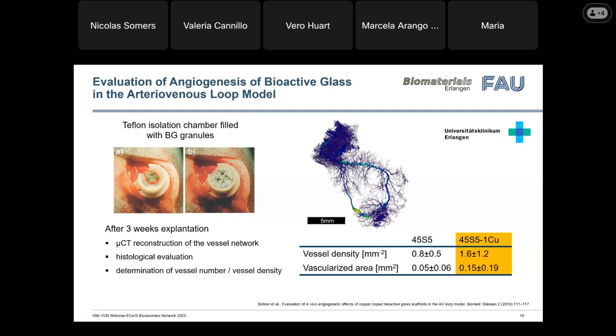And then vascularized tissue is formed, and parameters such as vessel density or vascularized area are measured. Here we can see that for the glass with copper, these values were higher compared to the reference composition.